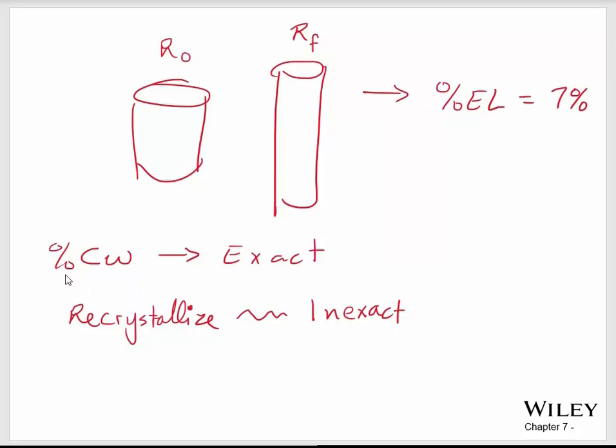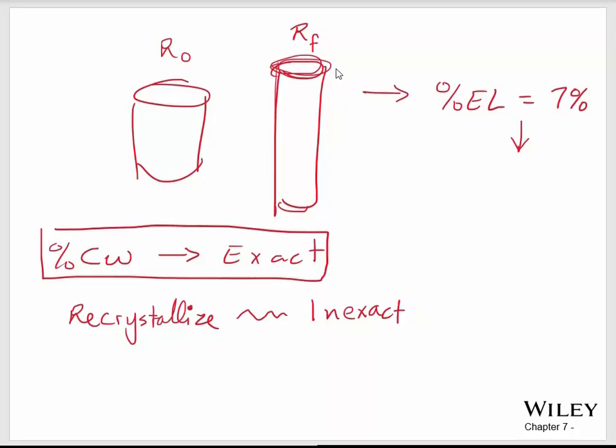So our method is to cold work as we need, and then if we need to reset the material, we could do that for this new piece of copper that we had previously drawn out. We can reset this percent elongation to its original by heating it, right? And then we can cold work it some more, and then we can reset it, and we can cold work it some more, and we can reset it. So what we really want in order to cold work something exactly to spec is to keep resetting it until we're ready to cold work it exactly to the amount that we want. So keep that in mind as we address this new problem.